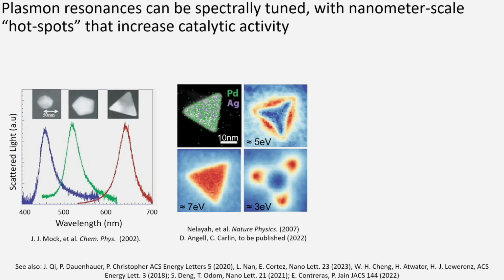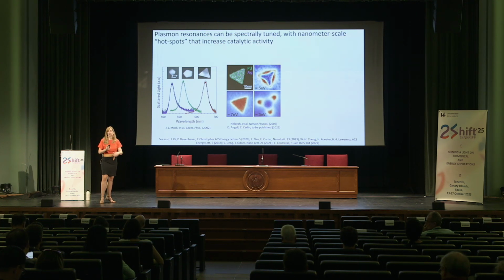And just to illustrate that in a little bit more detail, there's been a long history to this field, but with plasmons, so optical excitations of metallic nanoparticles, you can control the scattering or the color of those nanoparticles. So you can take, say, a silver or a gold or a palladium nanoparticle and tune the color simply by tuning the shape of the nanoparticle. So here what we're looking at is basically the color of light that gets scattered for a certain metallic nanoparticle, just changing the shape of it.